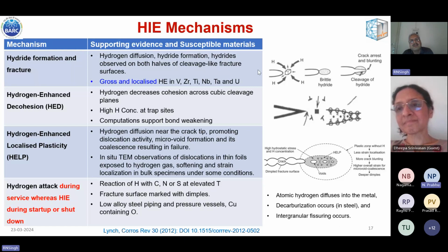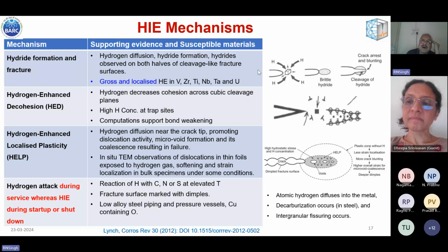But our concern is that as far as hydride embrittlement is concerned, you don't need any specific facility. A normal mechanical facility with hydrogen charging, and conventional sample geometry, can be used. The major concern is testing metals like austenitic stainless steel, where in order to pump hydrogen into the metal, you need a hydrogen pressure of some 100 MPa. So for that, a specific facility is required. Another thing that could be considered is pre-charging, but again, the fugacity is very high.